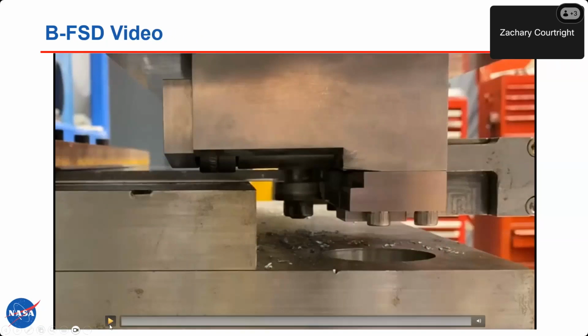Before we show the video, I did want to mention that because it's a Bobbin Friction Stir type deposition, it can also be used for self-reacting tools. If you have that secondary axis with a self-reacting tool, you could actually open and close to increase the thickness of the deposition. Say you were building a stage or a cylinder or a pipeline. You could be depositing at a monolithic thickness, but once you get up to a point where you want a little more stiffness or you have more stress concentrations, you could thicken that area over a number of passes and have a built-in stiffening capability. So that's one of the interesting advantages.